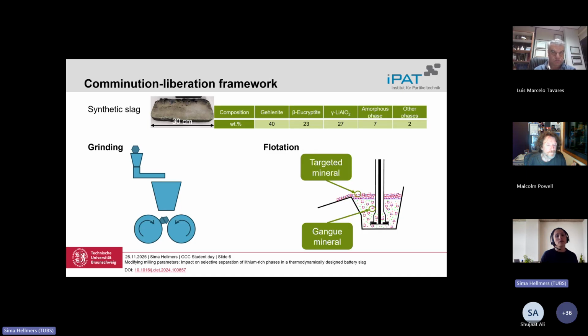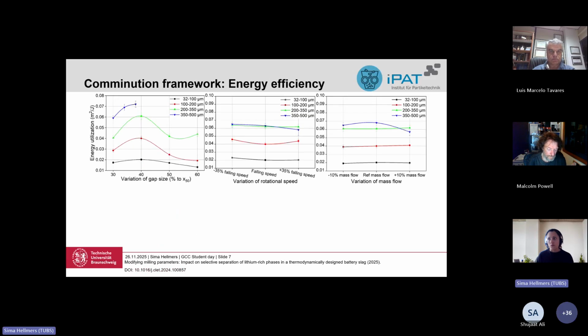I used several different crushing steps until I got to 500 micron. Then I used different feeds with a double roll mill to have a very narrow distribution of particles, so I could study the effect of particle size in flotation. How did it work? There were 3 different parameters, one of them was the speed of the roller. The idea was to use different gap sizes and different rotational speeds, and of course change the mass flow. What could be measured was the specific energy, to see which of these variables are efficient and which are not.